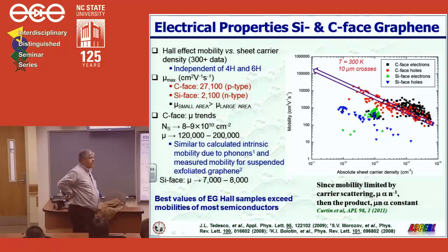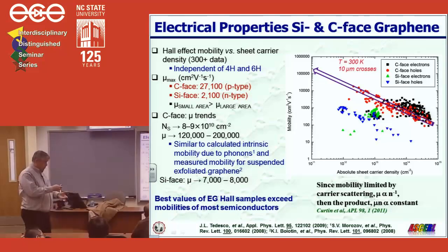For using the standard process of just growing it at 1,560 degrees, it's about 1 times 10 to the 13th, and it's N-type on the silicon face. We haven't done much on the carbon face since this data went out, until we learned how to control it to 1 or 2 layers.